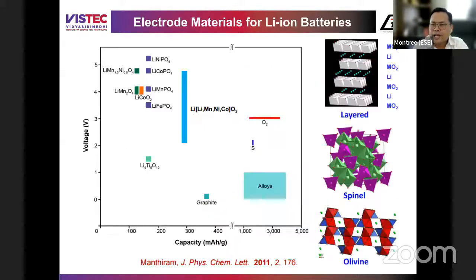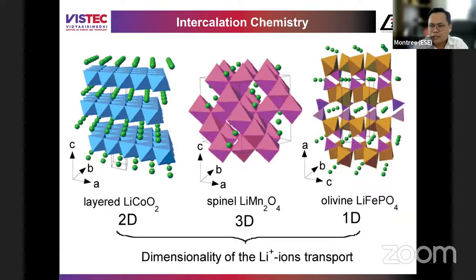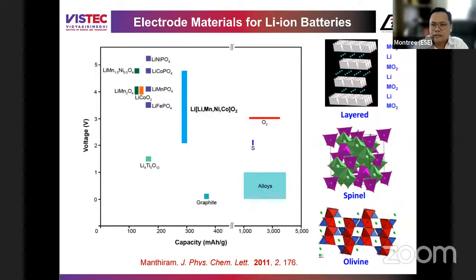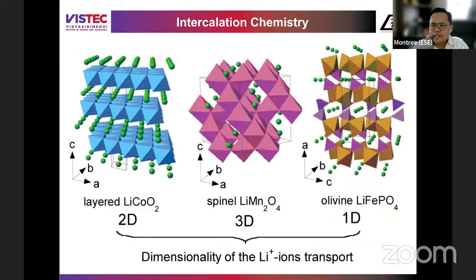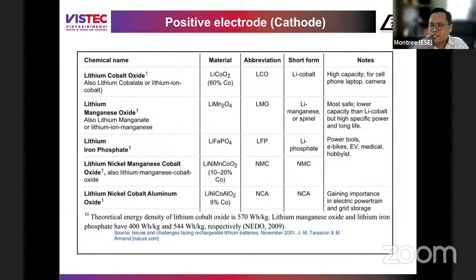And then you can look at that. The anode side can be graphite, which is the most available one, the best one so far, and LTO, and the alloy one. The cathode, they have a lot of options, LFP and so on, and NMC, right? And here you look at the structure. If you have layer material, it gives you high energy, but very fragile for the structure. It easily collapses. If you go to 3D, 1D, you have connectors, you have the bridge here, it's more stable, but you get lower energy, right? There is no single universal battery that trades off. So the property depends on the application.